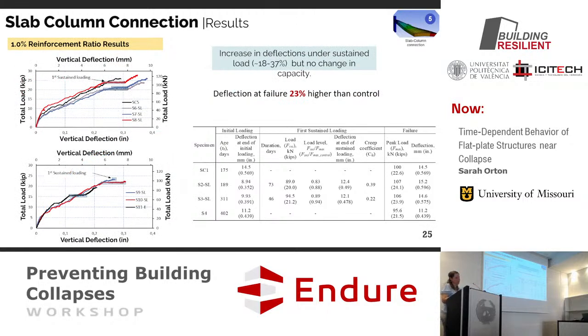For the other tests, we cut it off a little bit here, but 1% is a higher reinforcement ratio. In those tests, the black one's the control, and you can see the test ones have about the same capacity, but the deflection at failure is around 23% higher than the control specimen. The ones with the higher reinforcement ratio tend to be controlled more by the shear behavior, but under sustained load, because the concrete's creeping, it's allowing a lot of deflection. And so you're able to pick up a lot more deflection in the ones with the higher reinforcement ratio than you would under short-term loading.